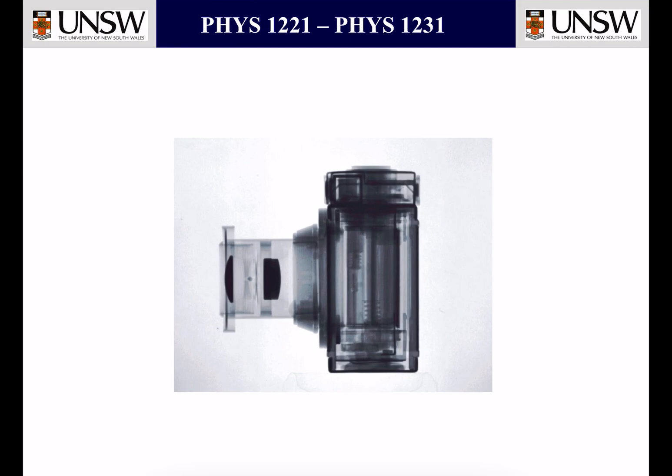Here's the side view of the camera and now you can nicely see the lenses. In those years they used boronated glass, and boron is strongly neutron absorbing, which is why the lenses are pitch black. But if you have a closer look, the second — thicker — lens actually has two slightly different grey shades, because two different types of glasses are glued together. The trick here is to compensate for chromatic mistakes.